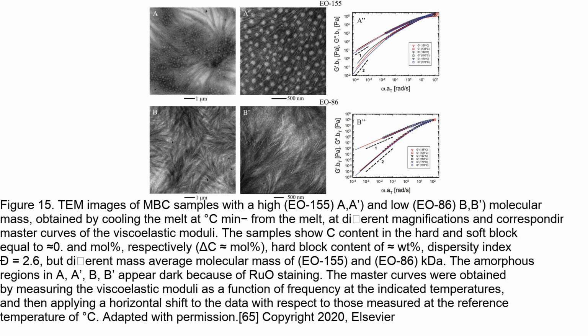The TEM images obtained by slow cooling from the melt to room temperature show PE lamellar sheaves typical of spherolitic superstructures for both samples. However, the EO155 sample exhibits brighter round domains within the sheaves compared to the EO86 sample. This indicates mesophase separation in the solid state for the EO155 sample and a more homogeneous lamellar arrangement for the EO86 sample.